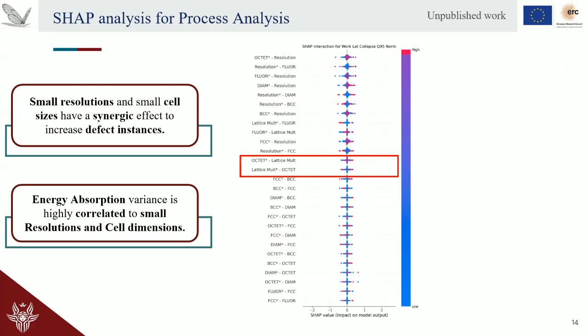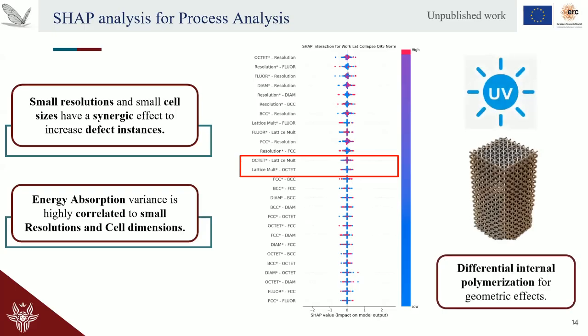So there is some synergistic effect between the topology, the cell size, and the resolution. But why that? The motivation is very simple, because the octet cell is very dense. And when I decrease further the cell size, I increase a lot the density of the cell. Since after washing, I had to post-cure the specimen, the light wasn't fully reaching the inside of the component. So inside there are a lot of under-polymerized regions. And this was fully confirmed by observing the fracture surfaces of the specimen, because inside it wasn't fully polymerized.